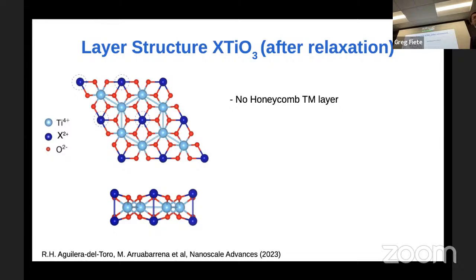You see also that all the 2D materials we have done are almost in the same magnetic structure: antiferromagnetically coupled between up and down, and ferromagnetically coupled on the top. But you notice that, for instance, the manganese compound, as in the bulk, prefers to be antiferromagnetically coupled in the layers, and then antiferromagnetically coupled between layers. So it's a completely different structure.